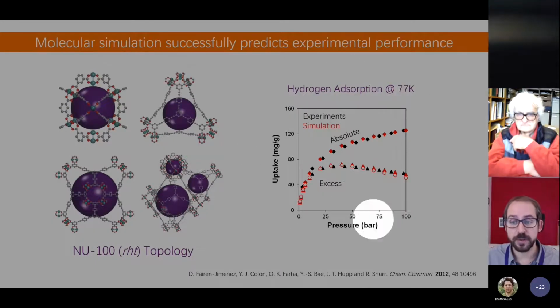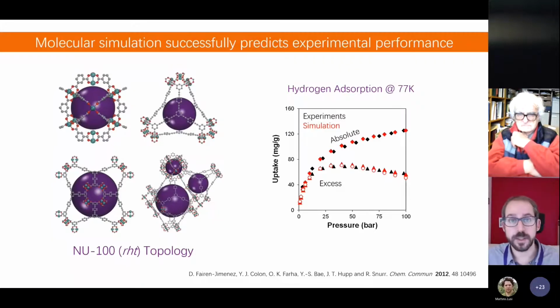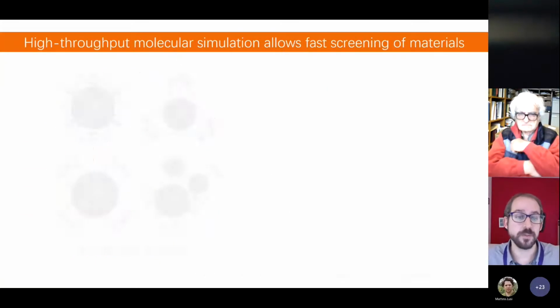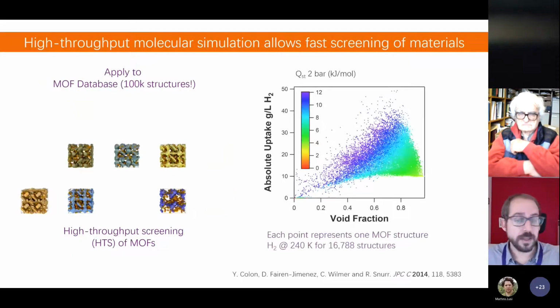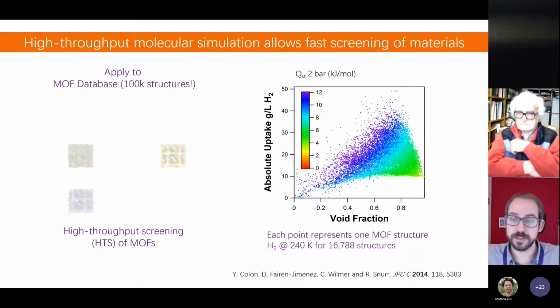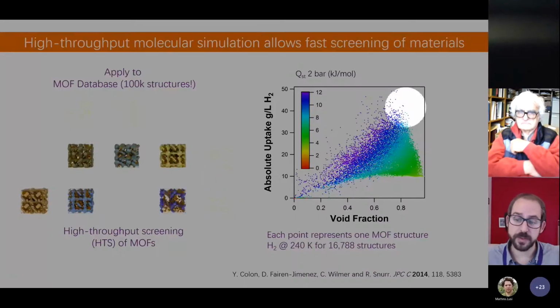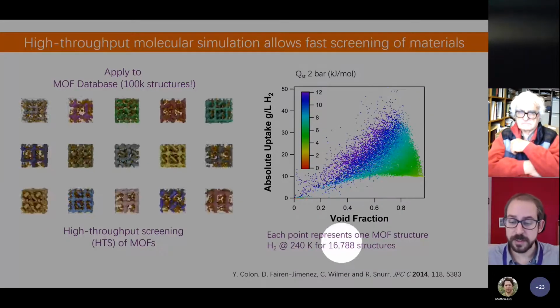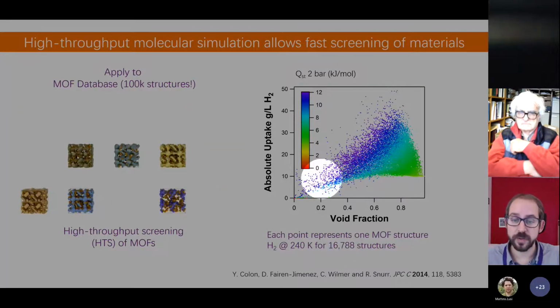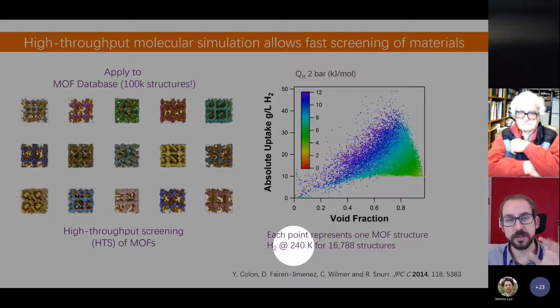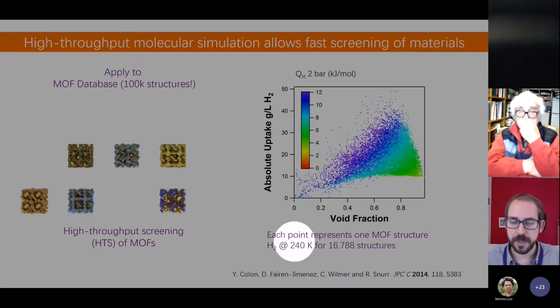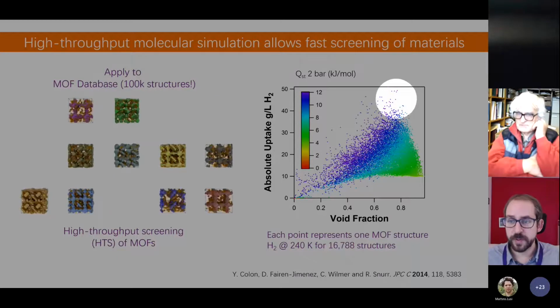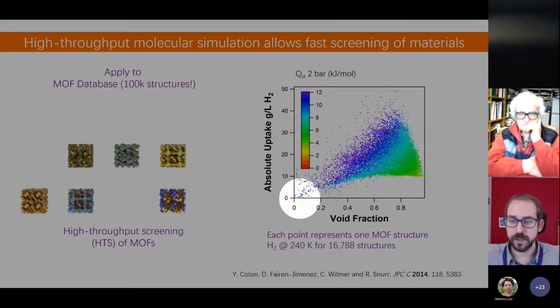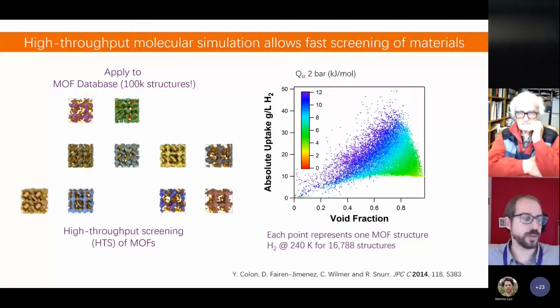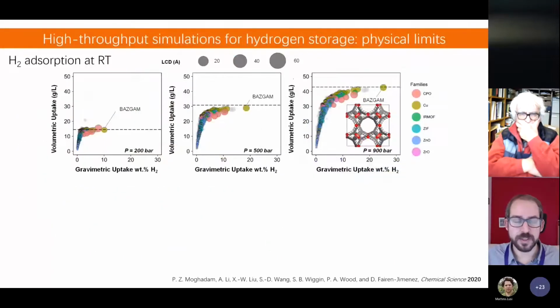And this means that if we can do this for one single structure, we can obviously take a whole database of materials and start running all the simulations in parallel. And this is basically what is shown in this slide. Every single point you see here is the result of one molecular simulation, 16,000 different points, different metalorganic frameworks for hydrogen storage at low temperature, but not cryogenic temperature. You can see MOFs that perform extremely well, MOFs that perform not that well, and you can also see all the different components. So we take all these different ideas and we can also extend this for different conditions.